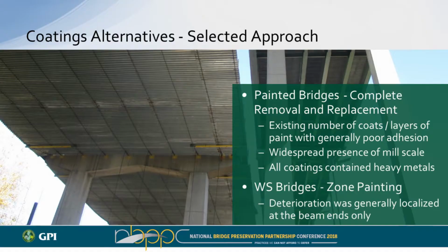For the weathering steel bridges, we went with that zone painting. Again, primarily because the deterioration was limited to the beam ends and within the splash zones. There were a few unique scenarios. A couple of the bridges had longitudinal joints where the chlorides were getting down in between.